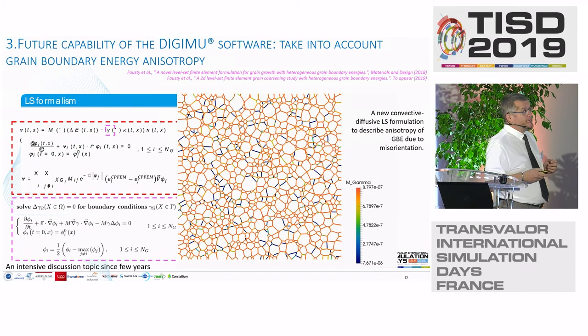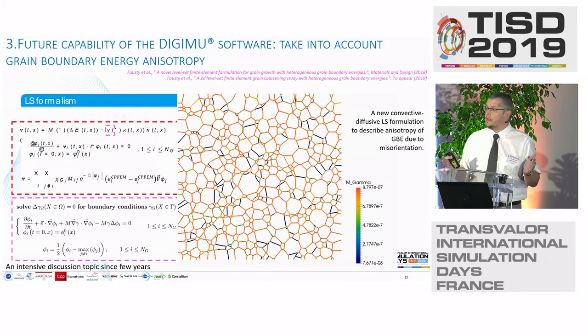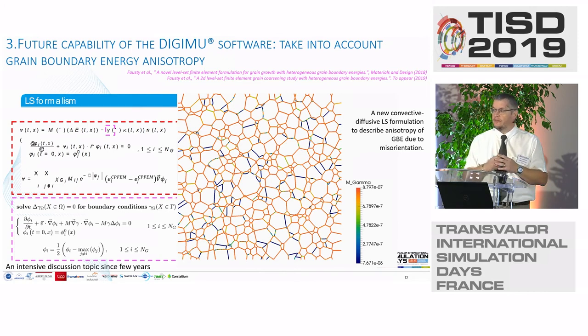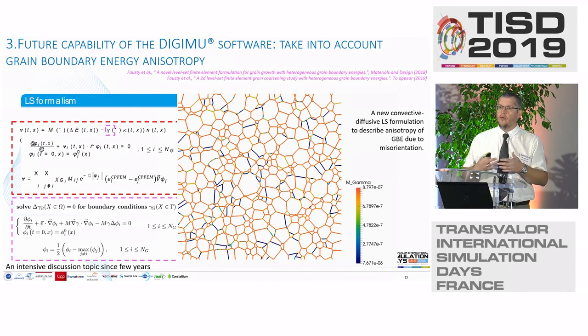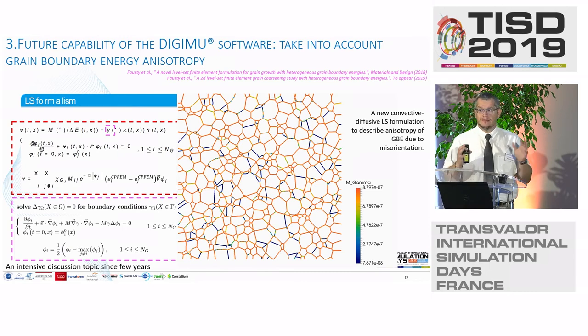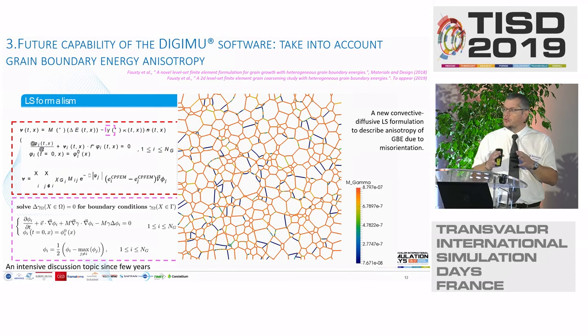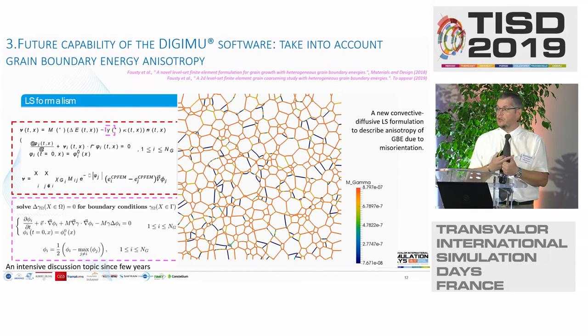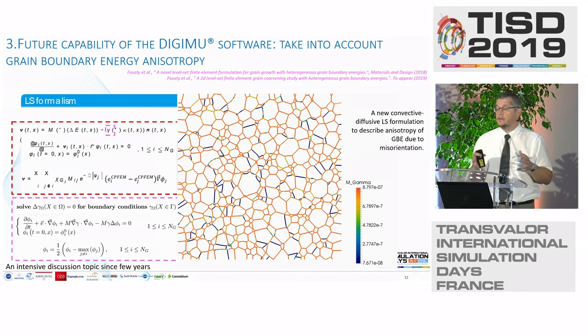Another hot topic for microstructure modeling is to take into account what we call special grain boundaries. If you have for example a grain growth experiment where blue interfaces are twin interfaces, a key question is whether it is really important to take into account orientation — for example using the Read-Shockley formulation — to describe grain boundary energy. What we now know from our development is that if you have only a mildly textured material with small anisotropy of grain boundary energy, taking this anisotropy into account is not interesting because the simulation becomes much more complex with no significant difference in prediction compared to isotropic simulation.